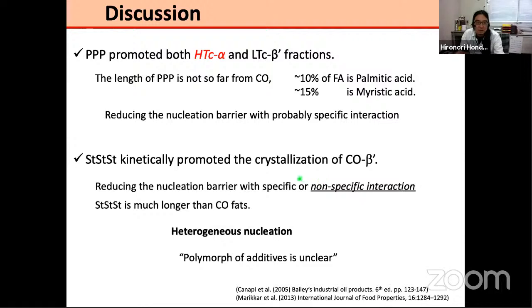of course, if the condition was different, this CO beta prime can be crystallized directly from the melt without the tristearin. But with the tristearin, I think these additives can provide some interface for specific or non-specific interaction. It is not sure yet, but the tristearin is much longer than the coconut oil. So I guess it's a non-specific interaction, and the surface can promote any crystallization by heterogeneous nucleation. So with this effect, the crystallization barrier for the coconut oil beta prime was reduced, and this stable form can be crystallized.